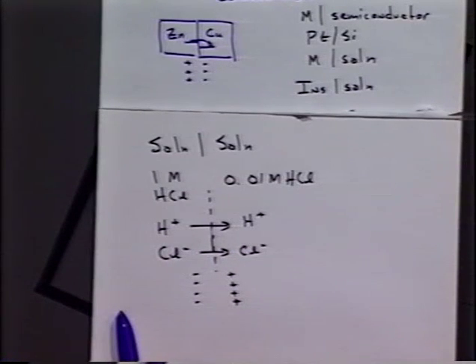And so that suggests that there will be a net potential buildup at that interface. In fact, that's what we see. We get a positive potential at the lower concentration of HCl compared to the solution that has the higher concentration of HCl. And that's not an insignificant potential. It can be a few tens of millivolts. It's called a liquid junction potential.